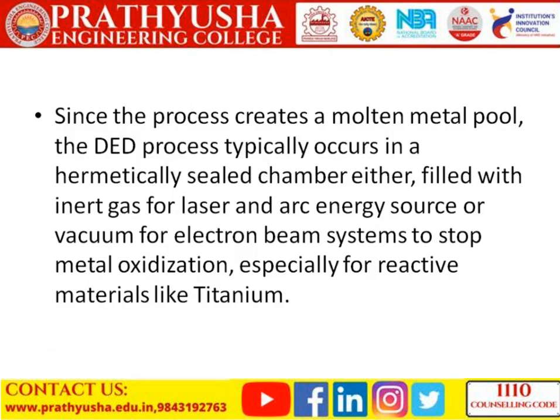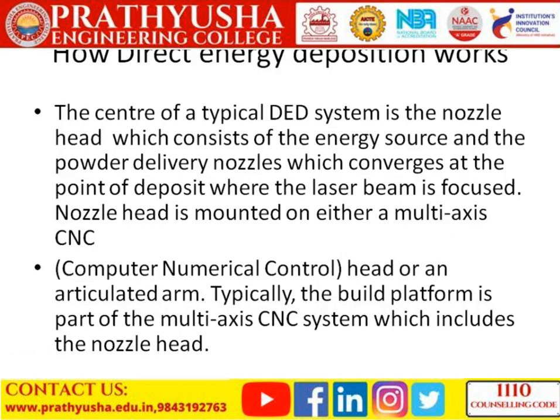Since the process creates a molten metal pool, direct energy deposition typically occurs in a sealed chamber filled with inert gas, or under vacuum for electron beam systems, to prevent metal oxidation — especially for reactive materials like titanium. The center of a typical direct energy deposition system is the nozzle head, which consists of the energy source and powder delivery nozzle converging at the point of deposit, mounted on a multi-axis CNC machine.